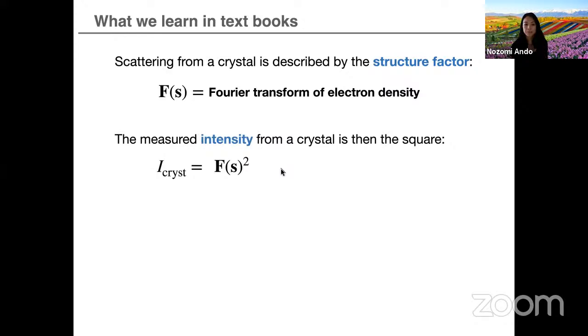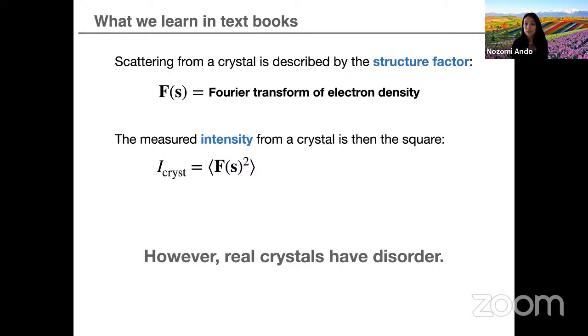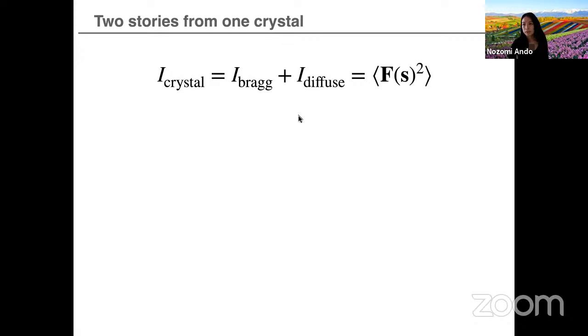However, I already told you that a real crystal is not a perfect crystal. There's always some disorder, which we model even within the crystal structural model, in terms of B factors. So what we're actually measuring is the ensemble average, or what we assume is the time average. So we put brackets around the structure factor squared. And there's a consequence to that, which is that the total scattering from a crystal actually has two components. There's a Bragg component and the diffuse scattering component.